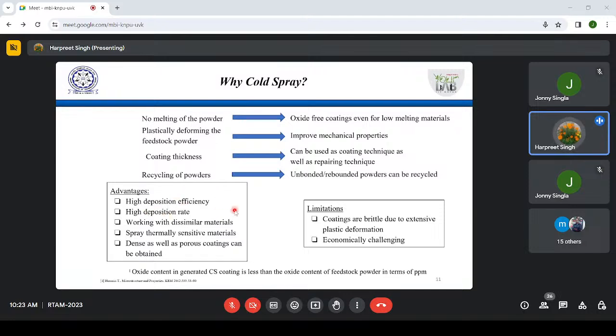Another attribute is high deposition efficiency, if you compare it with other processes, and of course high deposition rate. Now this is a very attractive feature here. High deposition rate means, for example, with our system, if everything is optimized, you can achieve say 10 to 12 kg per hour deposition, which is very good actually. In your conventional manufacturing processes, this cannot be achieved so fast, right? So we can deposit at very high deposition rates, and that is something which makes the cold spray process attractive for manufacturing.